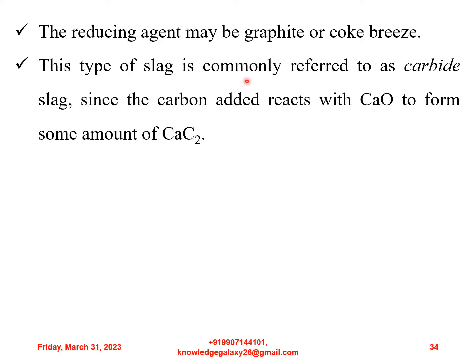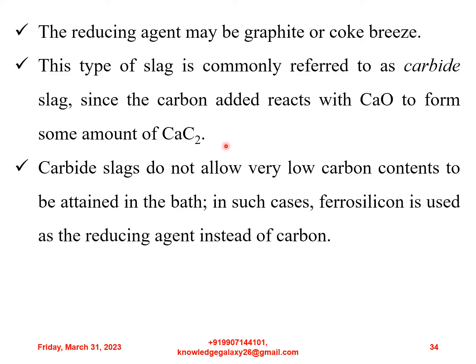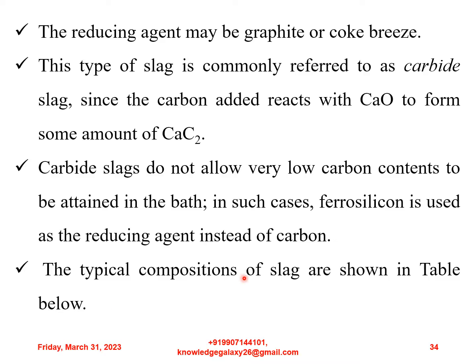The reducing agent may be graphite or coke breeze. This type of slag is commonly referred to as carbide slag since the carbon added reacts with CaO to form some amount of CaC2. Carbide slags do not allow very low carbon contents to be attained in the bath. In such cases, ferrosilicon is used as the reducing agent instead of carbon. The typical compositions of slag are shown in the next table.